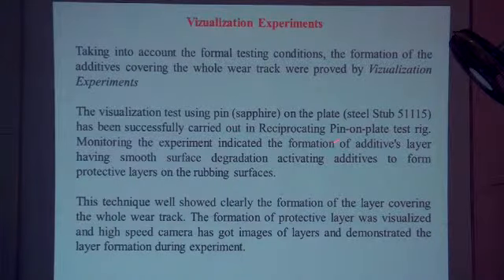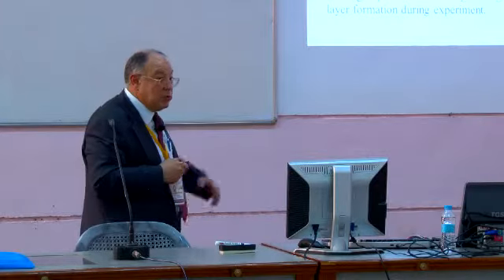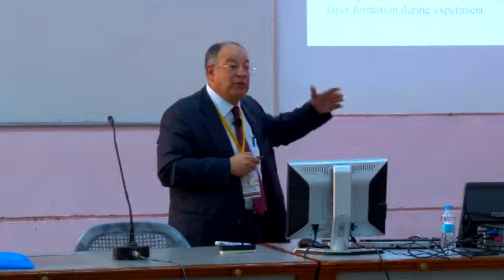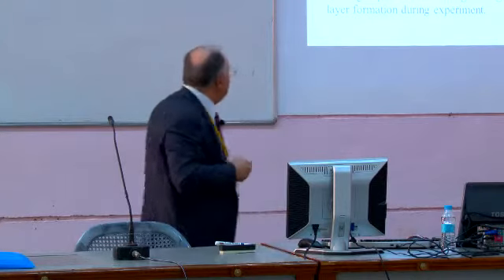This is the sapphire pin on the plate, and the steel stub. We ran the experiments where, under the same conditions and with a smooth surface flatness, we obtained additive layers on the surface.